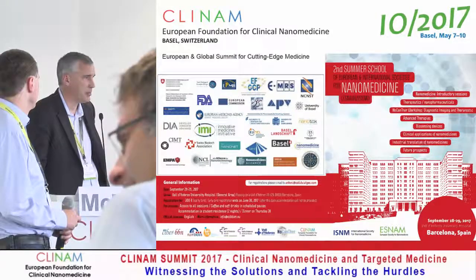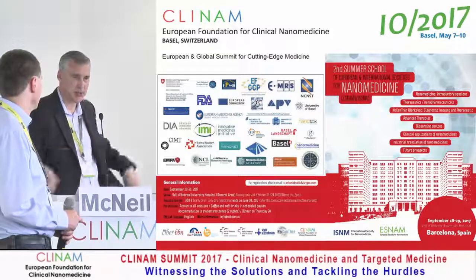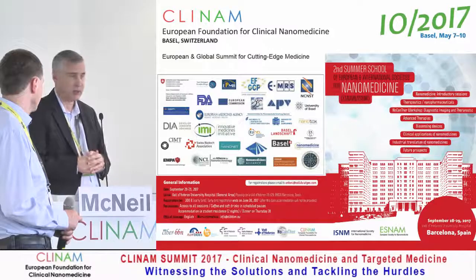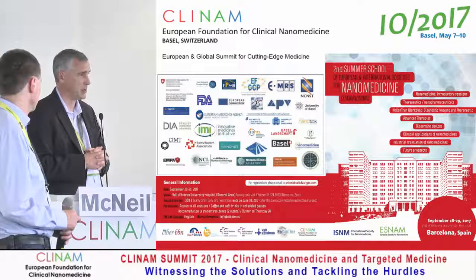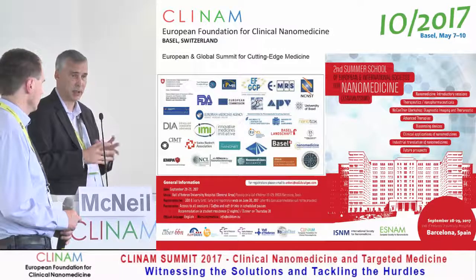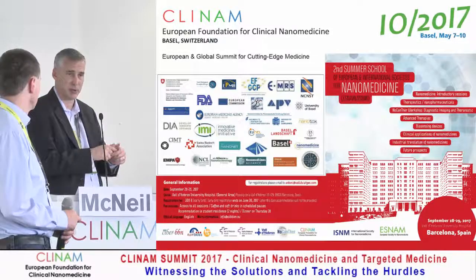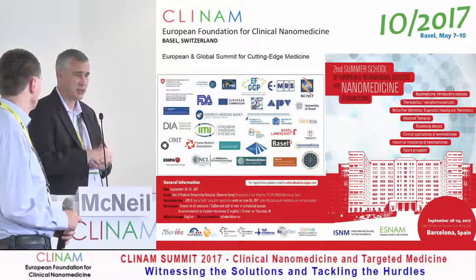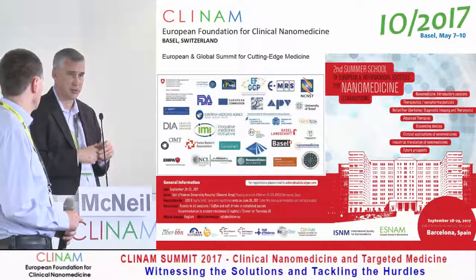Other molecules that we can use will often dual radiolabel. So we can look at if the drug comes apart from the nanoparticle, and we see that often. And other methods are just doing a solid support method if the particle will survive it. And again, it depends on which measurand you're going after. As long as you don't care if the particle falls apart, you can use that. Steve Stern in the lab has published a number of these, and his article in Journal of Controlled Release is a great starting place.